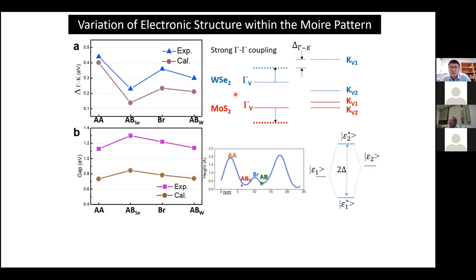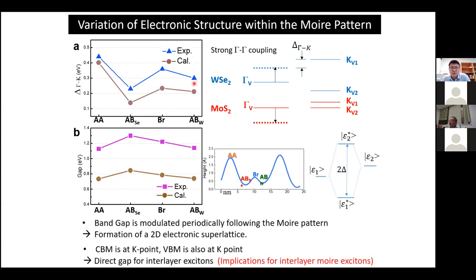Now let's look at the different sites. The AA site is where the two layers have the largest spacing, so you expect a smaller gamma-gamma coupling. And indeed, smaller gamma-gamma coupling will result in a larger separation between gamma and K. And that explained the whole result quite nicely. So we're quite happy.